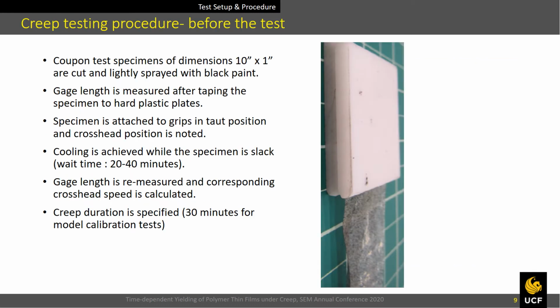Coupon specimens are lightly sprayed with black paint. Plastic plates are used to grip specimen without damaging the material. If it is a sub-room temperature test, depending on the temperature, 20 to 40 minutes is allowed while the specimen is slacked to achieve uniform temperature field inside the chamber. This also ensures material is not pre-stressed before the test due to thermal strains. Finally, before the test, creep duration is specified.